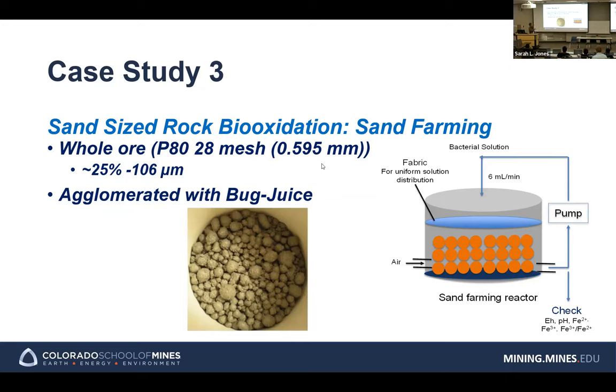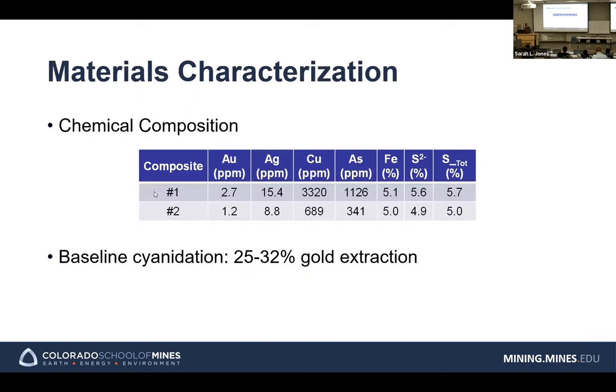The whole ore is 80% passing 0.6 millimeter. We use this reaction cell, and in the cell we put the agglomerated ore. This is the actual photograph of agglomerated ore in place in the reactors. We provide the air and the solutions, run this over a certain time, followed by the cyanidation gold extraction. And the ore is agglomerated with the bio solution. I said produce, and the microbiologist doesn't like it.